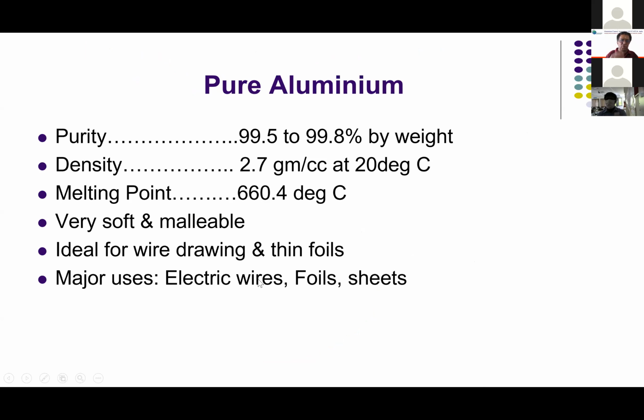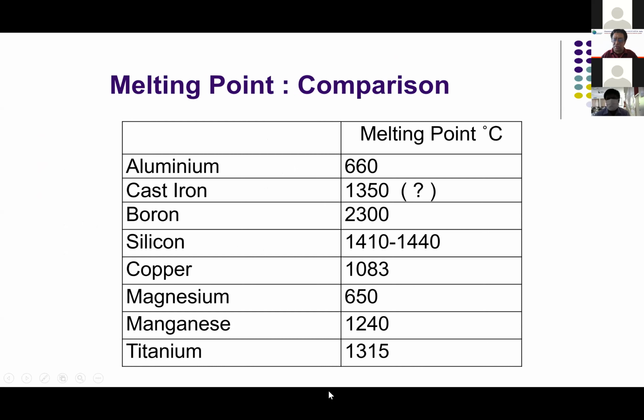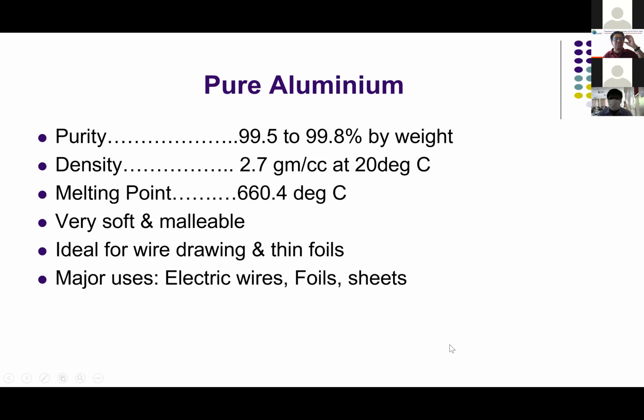Now let's come back to pure aluminum. When you say pure aluminum, it's about 99.5% to 99.8% pure by weight. Density, you all know, is 2.7 grams per cc. Pure aluminum melting point is about 660 degrees centigrade. The material is very soft and malleable, ideal for wire drawing and making very thin foils. Aluminum foils are extensively used in the packaging industry. Major uses: electric wires, foils, and sheets. This is the pure aluminum. There are also some castings made of pure aluminum. I'll come to that slightly later.